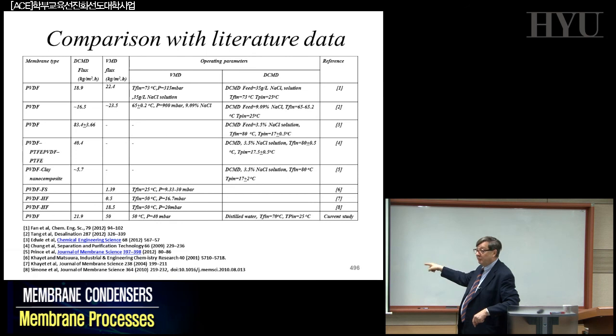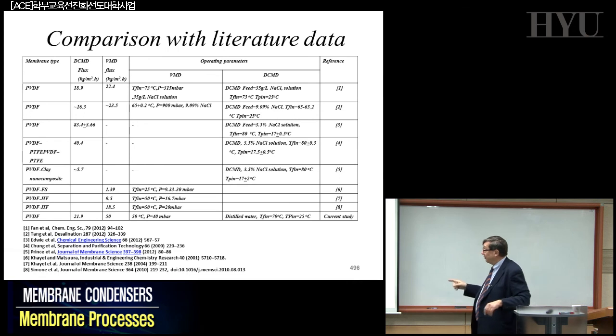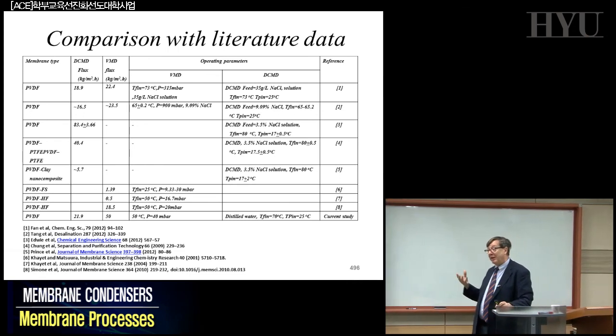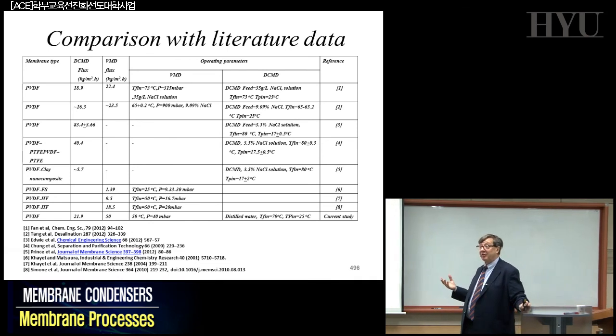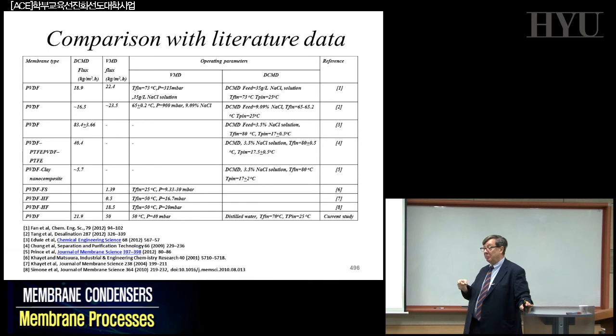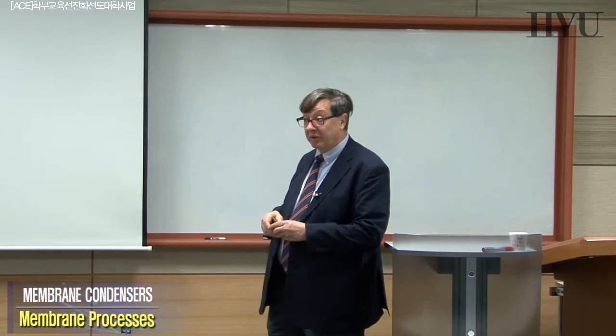Because if you want to use this membrane not for vacuum or direct contact, but for microfiltration, this is not necessary. Without considering that you have been learning, for example, that when you analyze in more detail the power efficiency, that means how much energy you are consuming, the thickness, which we have not been talking about here, is important because it controls the possibility of losing energy in warming up the polymers. If you increase the thickness a little bit, the efficiency increases in terms of reduced energy loss. So all these parameters are the ones that at the end give you results that can make progress compared to what is already in the literature.